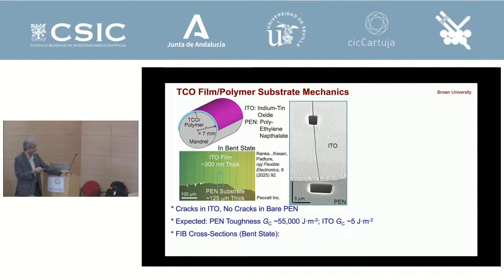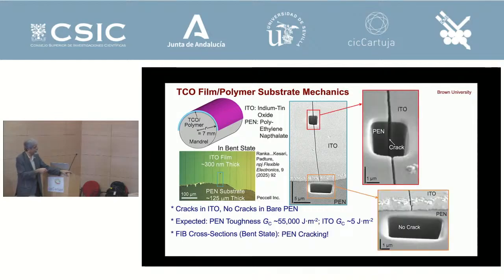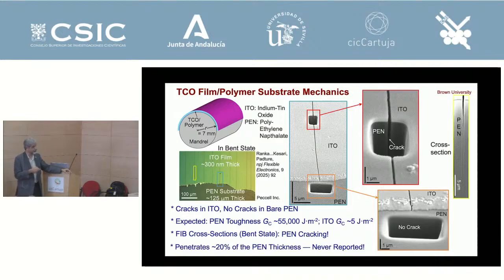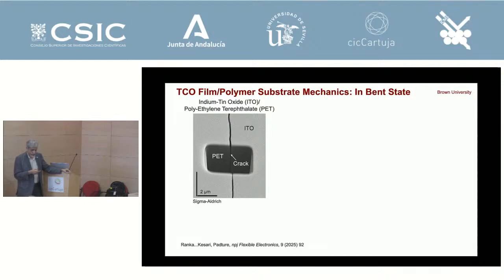But what he did was, he did focused ion beam here. And what he found, to his surprise and my surprise, is that the substrate, which is infinitely tough, is actually cracked. Where there's no coating, of course the substrate is not cracked, which is what we see here. But here, by FIB, you're able to reveal that under this coating, the substrate is cracked. And from all my mechanics education, this didn't make sense to me. And it kept me up at night, because, so what's going on? And I asked him, this is an artifact, let's do it again. And by the way, these cracks are so deep, they're 25 microns deep into the substrate, almost 20% of the substrate. And so he did it on different substrates.